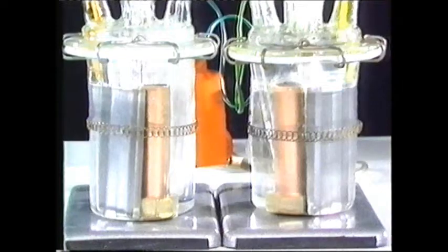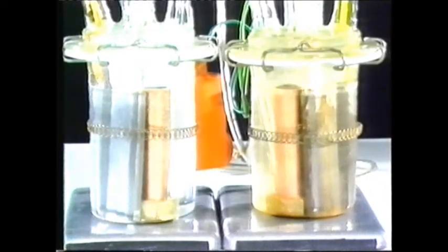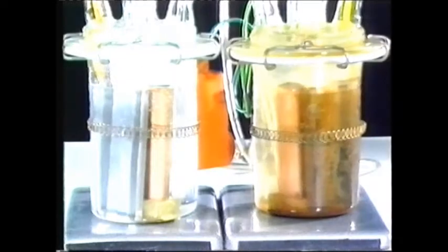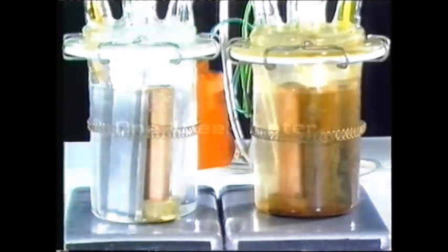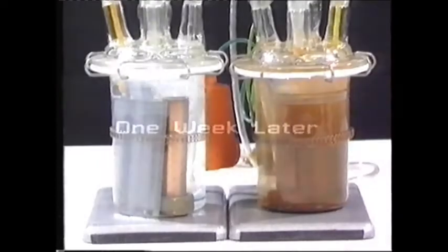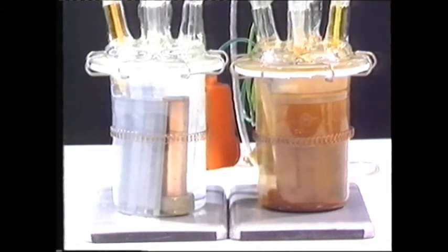After only half an hour, metal in the untreated water began showing signs of corrosion. 24 hours later, and clear signs of corrosion can be seen. A week later, and the difference is dramatic. Unlike the metal on the right, the metal in the Fernox treated water remains totally corrosion-free.